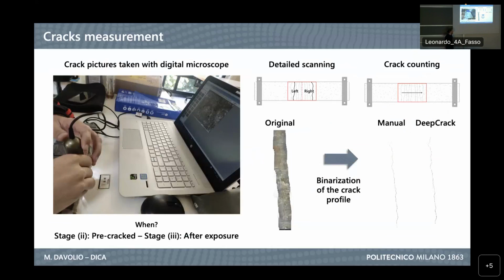This is the processing we did for the cracks. We could recompose the profile of the crack with the pictures we took from the microscope, and from that we binarized the crack to obtain the area. We tried 2 different methods. The first method was manual, which was very time-consuming, and for this we moved to a more automatic method, which was this deep crack code, which allowed us to just give the raw image to the software and obtain the profile of the picture of the crack. We also calibrated this method, observing how much was the difference between the manual processing and the automatic processing. And the difference was below 5%, so we accepted the automatic one as reliable.